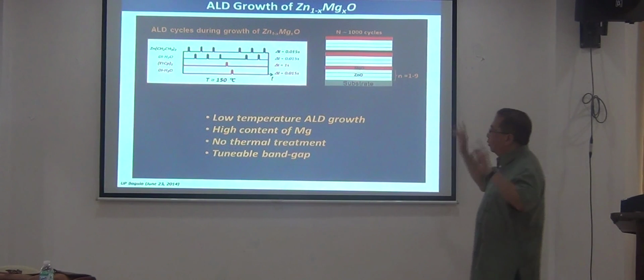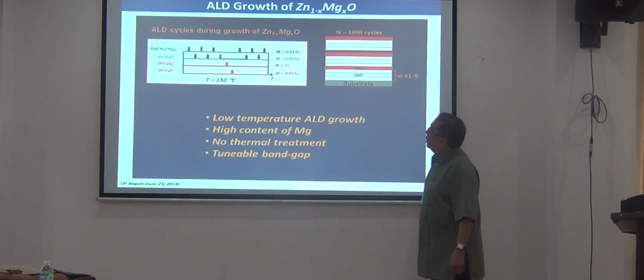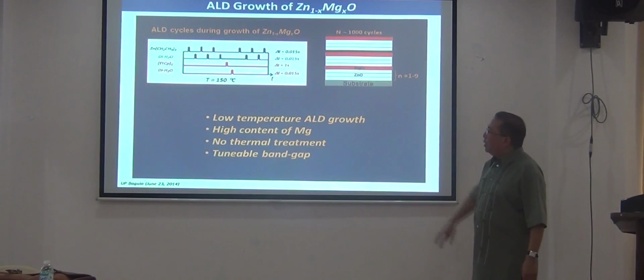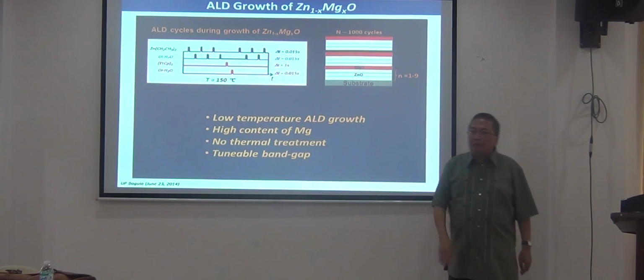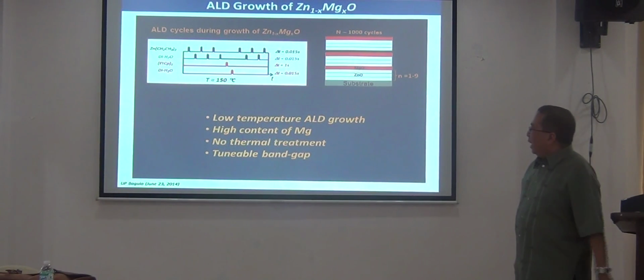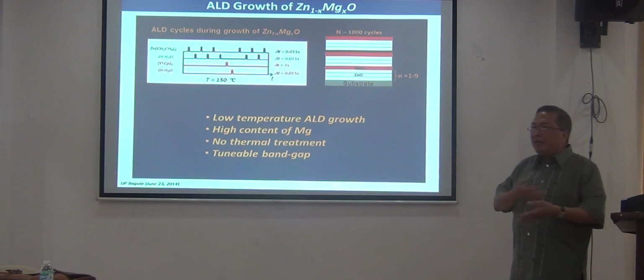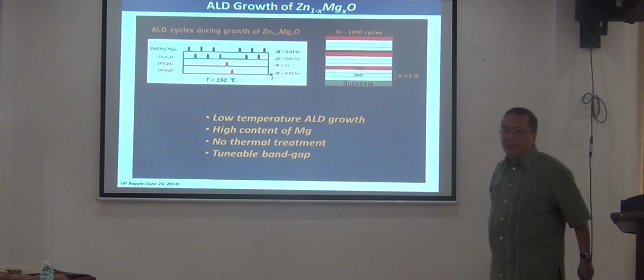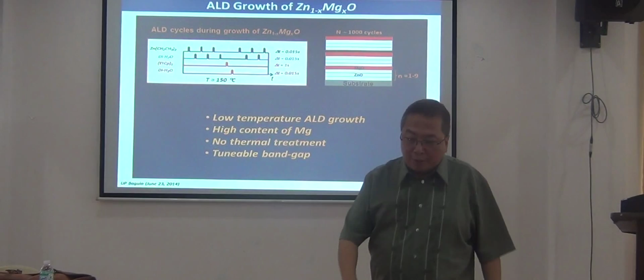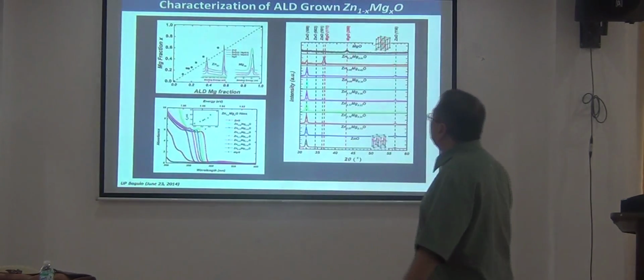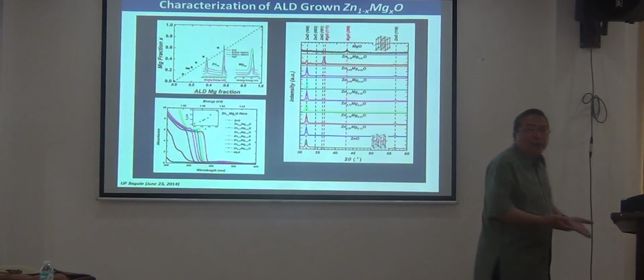And you're able to dope the zinc oxide with magnesium. You're able to do this at low temperature, and without any post-annealing or thermal treatment. And you're able to tune the bandgap again. How do we know that?